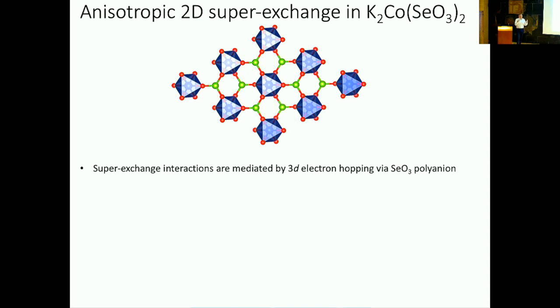So now I'm going to put that CoO6 degree of freedom on a lattice, and I'm going to use a polyanion, which is the SeO3 anion. This is a two-negative charged polyanion. That becomes the molecule that will allow 3d electrons to hop between different sites and will produce the exchange interactions. It also enforces the threefold rotation symmetry of the triangular lattice. And so that's all the beautiful chemistry that makes all of this possible. There will then be what we call superexchange interactions as a result of the electron hopping.